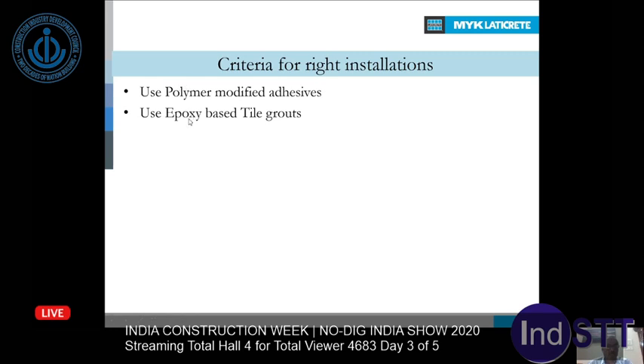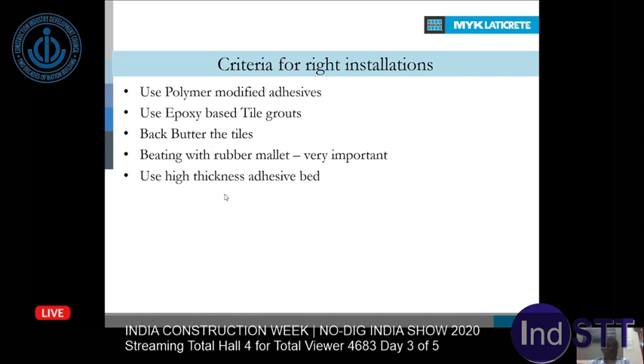And we also recommend epoxy based tile grouts for again the reasons we talked about just now. And it's very, very important that when we are using large format tiles, we back-butter the tiles so that the coverage is very uniform. And once done, certainly use a rubber mallet to beat to get a uniform coverage, so that the tile is keyed in with adhesive to the substrate in a uniform manner. There is no hollow sound, there are no open areas.